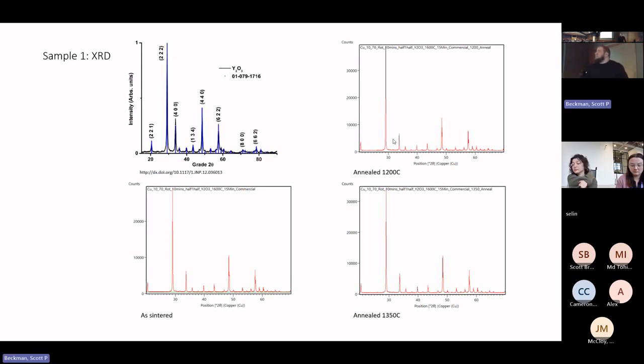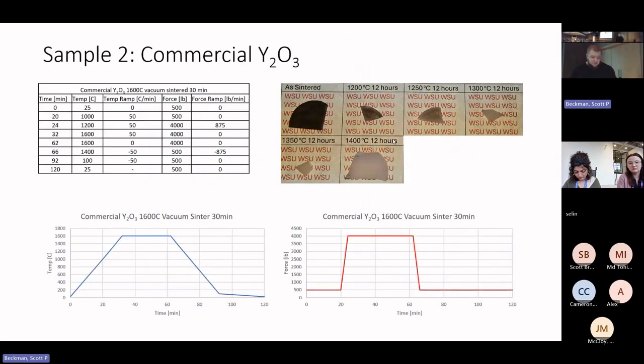We also did XRD analysis on our pellets to determine what phase was present in our Y2O3 samples. We were curious whether we'd see any inclusions that were separate phases, but upon doing XRD analysis, we found that we were basically only seeing Bixbyite Y2O3, which is exactly what we expected, and we weren't able to see any impurities or other phases. But the caveat is that I believe our XRD is only able to detect about 0.5% impurities. So if the impurities are a smaller fraction than that, we can't see them with the XRD, and we have to use a different technique such as Raman to look for them.